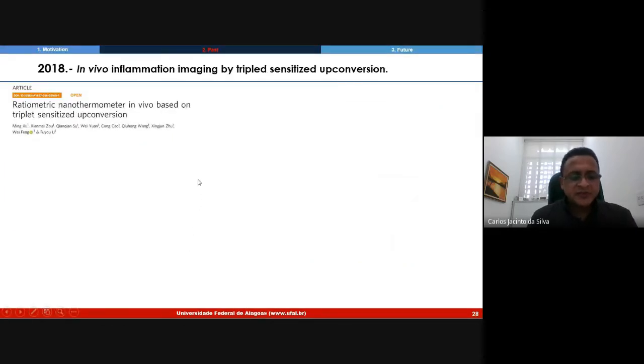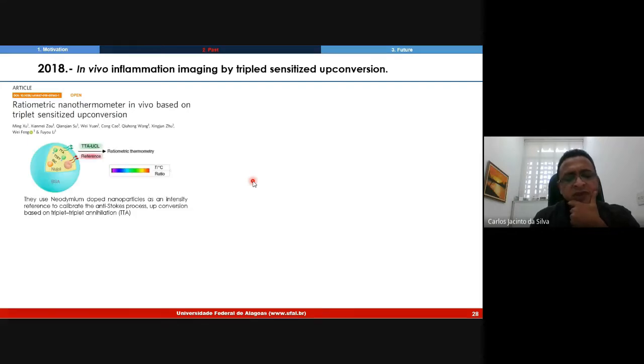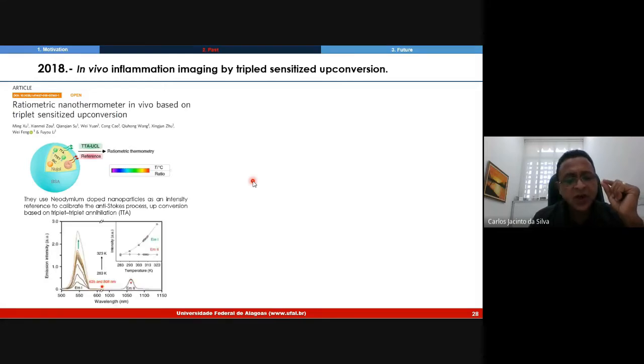As presented in this paper, the authors used a neodymium-doped nanoparticle as an intensity reference to calibrate the anti-Stokes process, upconversion based on triplet annihilation. A super sensitive ratiometric luminescence thermometer was obtained with a maximum relative thermosensitivity of 7.1% degrees Celsius minus 1, and it was used to do thermal imaging for rheumatoid arthritis diagnosis.